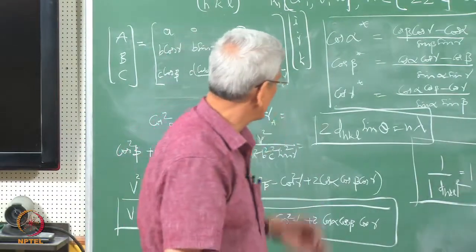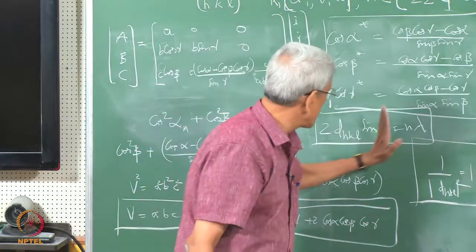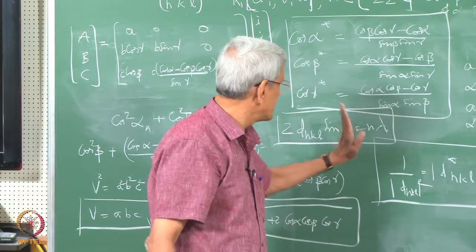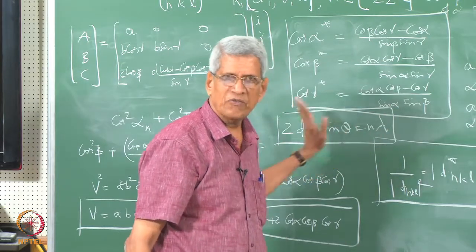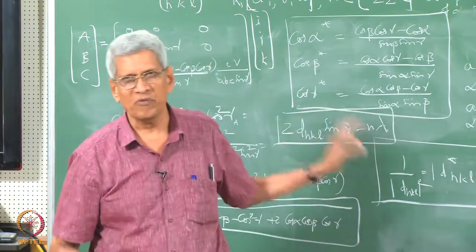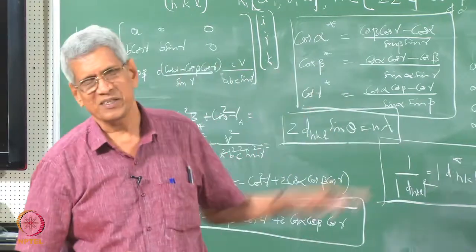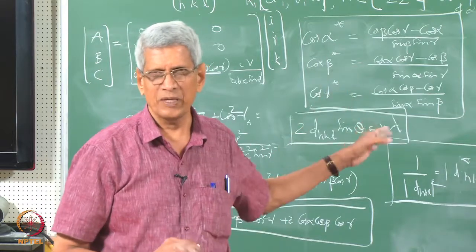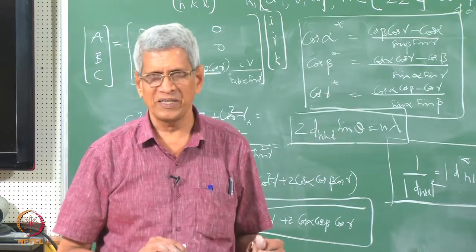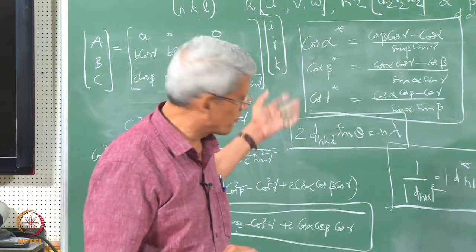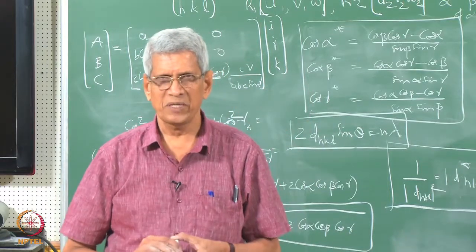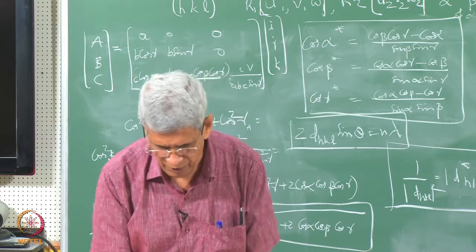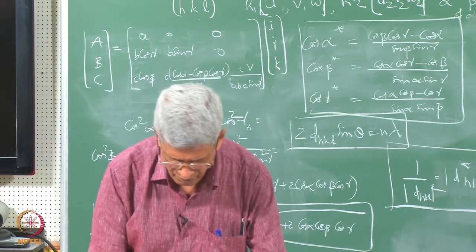So, the information we get is for a particular value of lambda which we use. What we get experimentally, from the value of theta, is only the d_hkl information, that is 1 by d_hkl, the information in reciprocal space. This way one can derive formulas for various structures.